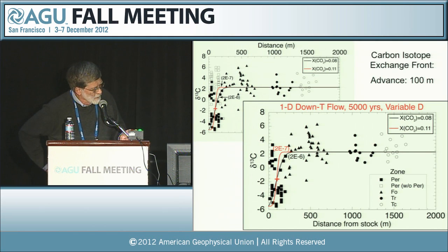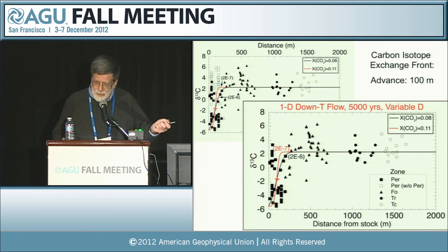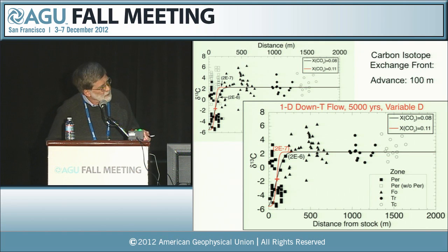Okay, so let's go on to the carbon isotope front here. Again, I've superimposed a couple of 1D model profiles at two values of the diffusion dispersion coefficient. The steeper one, at the lower dispersion value, might be a little better fit to the low delta C13 values. In contrast, the value of 2 times 10 to the minus 6 meters squared per second is the one that seems to fit the oxygen profile a little better. So there's a little bit of a difference here.